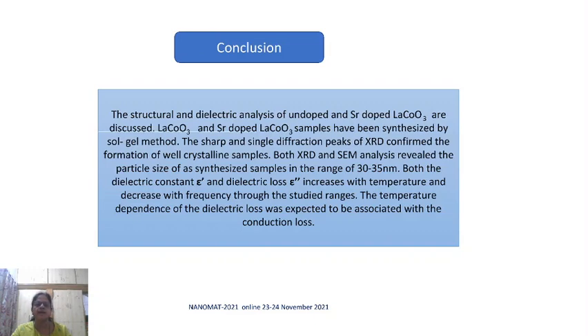Both XRD and SEM analysis revealed the particle size of the synthesized sample in the range of 30 to 35 nanometer. Both the dielectric constant and dielectric loss increase with temperature and decrease with frequency through the study range. The temperature dependence of dielectric loss was expected to be associated with the conducting loss.